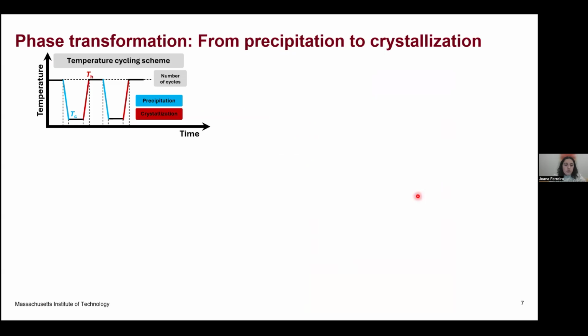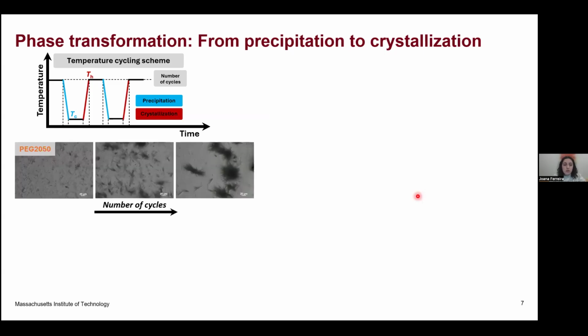So after this successful outcome, we also tried temperature cycling for one of the mAbs that we are dealing with here at MIT, because as you could see in the previous graph, it's very easy to precipitate a mAb. So we thought about temperature cycling as a strategy to suppress the formation of the precipitants while inducing the formation of the crystals. Here is one example. So we do the temperature cycling several times, so different cycles of cooling and heating continuously. And by increasing the number of cycles, we could see that we can suppress the initial precipitation, and at the end we can mostly observe crystals.